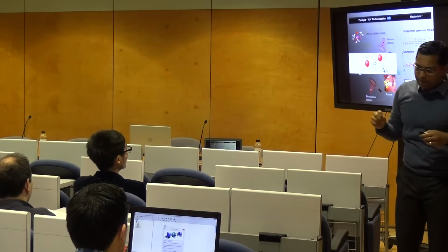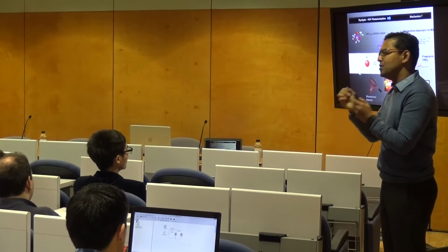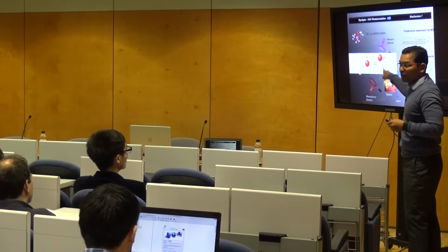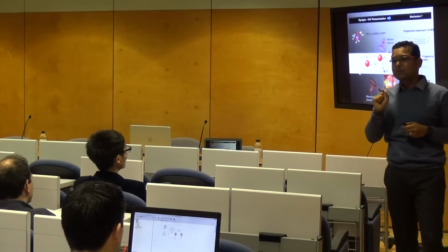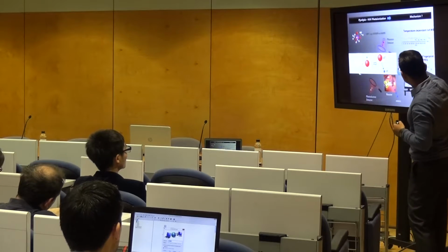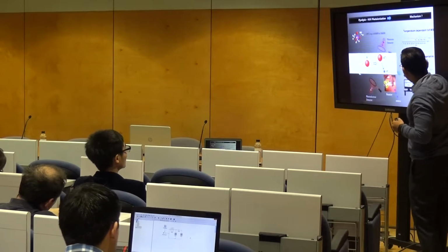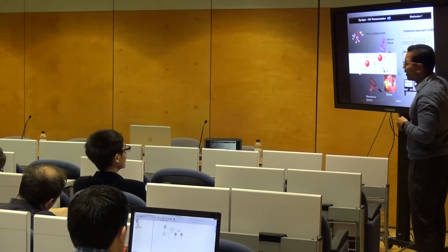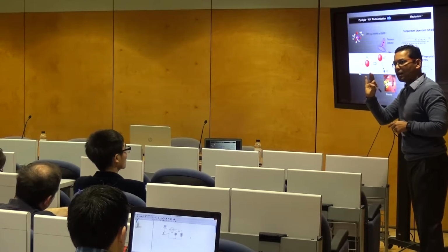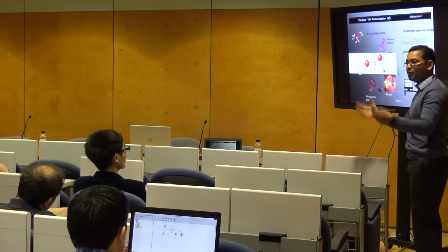And what is really nice is we are able to see the energy of the electron. Okay? And you know that the threshold photoionizing potential of each species is unique to its chemistry. Okay? So by mapping the electron energy, we can accurately say what species are being formed in this pyrolysis experiment. So you can see that's the mass spec data here. You see different masses being formed at different temperatures. But you also see there's a threshold photoelectron spectrum, okay, which is very specific for each species which are formed in a thermal decomposition process. Okay? And then by comparing both of them, we can come up with a nice mechanism.